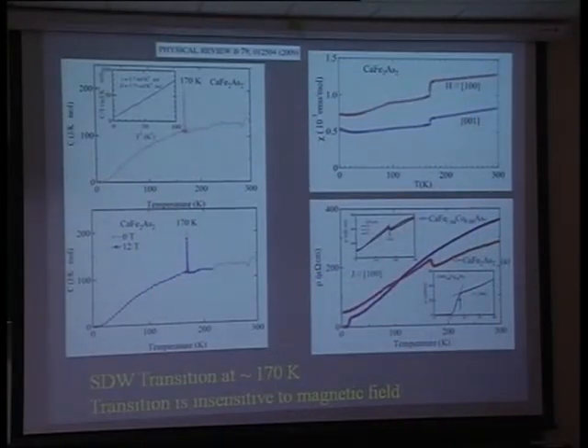You can see that this is a specific measurement done on the same sample that we have studied. It shows a sharp peak, although it has some width if you expand it. It is not like a delta function, of course, but it's quite sharp at the spin density transition around 170 Kelvin. Okay. And if you apply a 12 Tesla magnetic field, you see that this transition is not affected much. So actually this spin density state is really very stable. And this has been found in various magnetic susceptibility studies and so on. And resistivity also shows quite low values, a few micro ohm centimeter, you can see the metallic behavior.